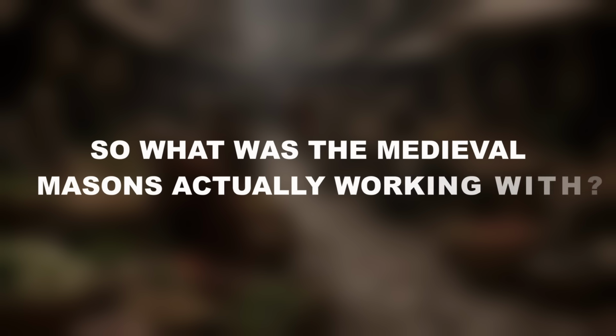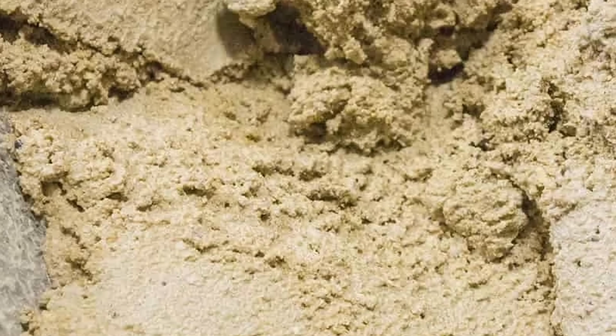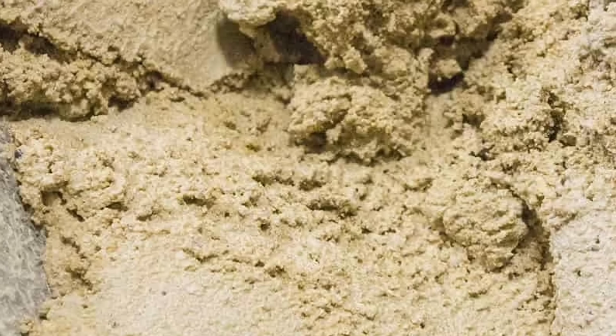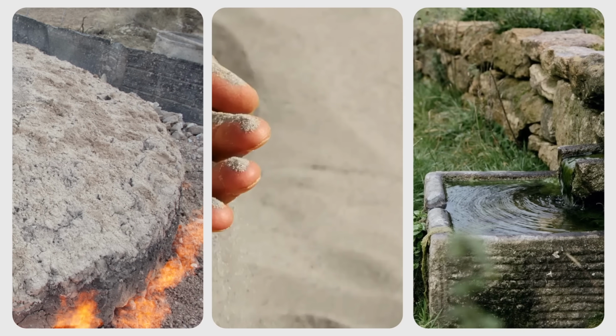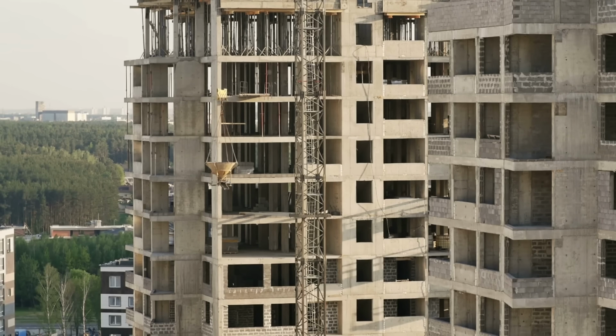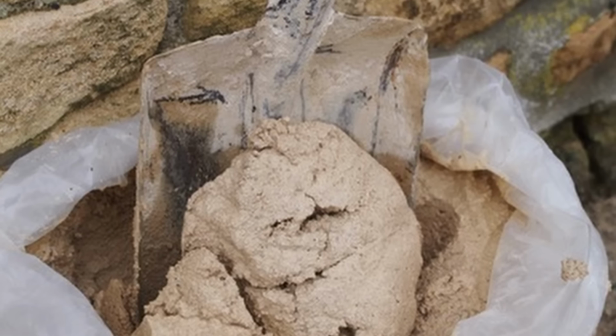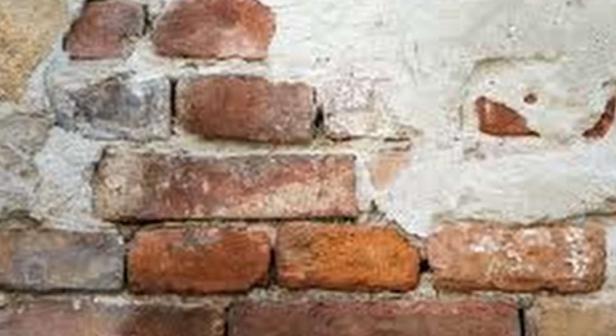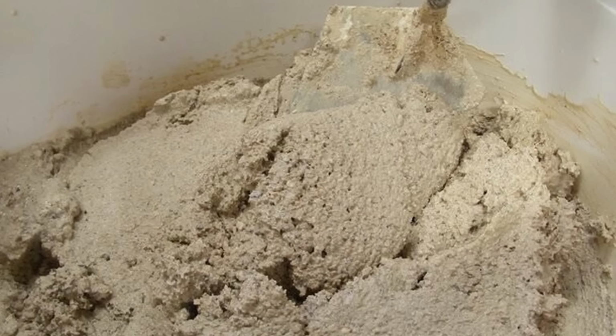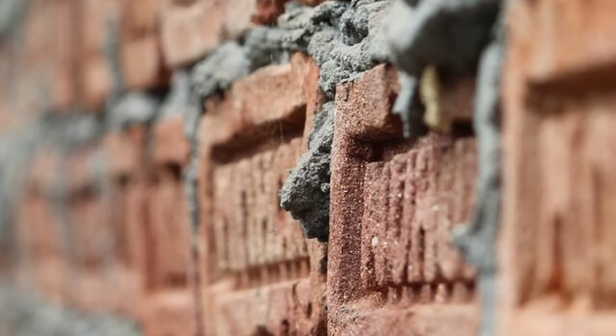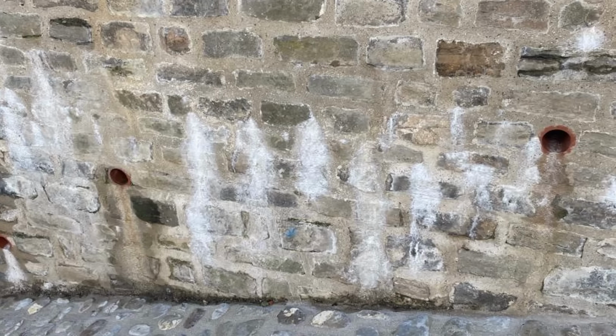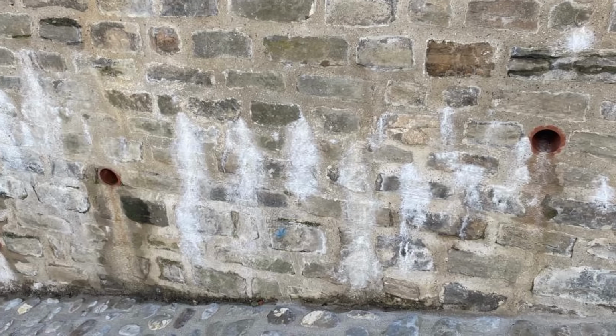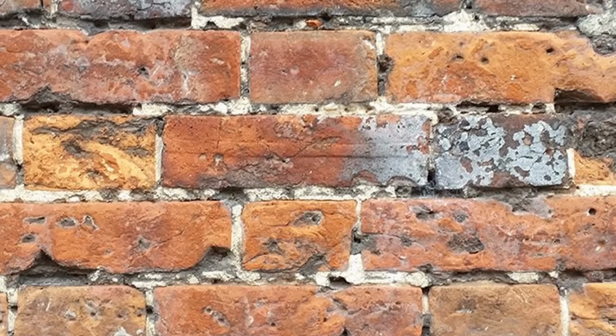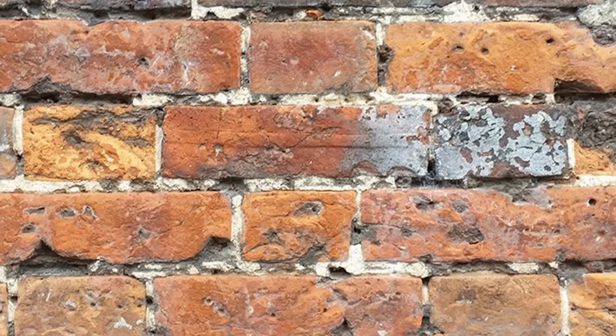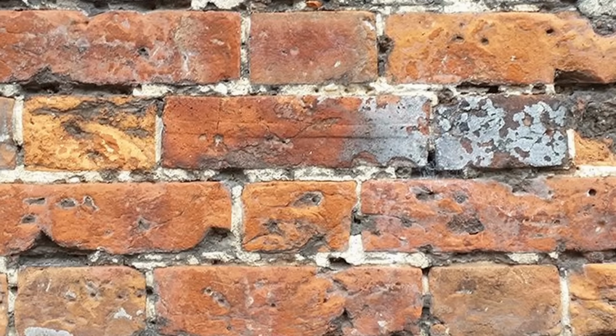So what were the medieval masons actually working with? It's called lime mortar, and it's made from 3 ingredients: burned limestone, sand, and water. Here's the part modern construction lost. Medieval lime mortar is a living material. When a hairline crack opens in a medieval joint, rainwater seeps in. It dissolves a tiny amount of reactive lime inside the mortar. That solution flows into the crack. Then it recrystallizes as calcium carbonate, the same mineral that formed limestone in the first place. The crack seals itself. The wall repairs its own wounds, decade after decade, century after century.